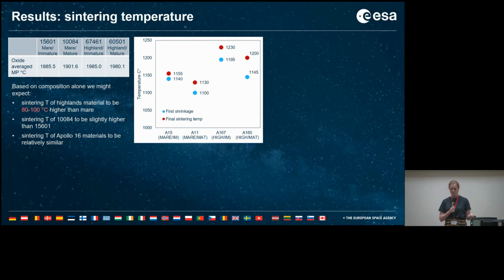So the red being the final sintering point when the material was very well sintered, and the blue being the sintering onset, so when it first shrunk away from the walls of the crucible and was removable as a pellet. And so here we can see that the Highlands material in general does sinter at a higher temperature than the Mare material. That can be reasonably well predicted with the composition. However, the other two predictions, we don't see that at all. So we would expect the Apollo 11 to have a higher sintering temperature than Apollo 15, but in fact it's quite a bit lower. And we see quite a variation in the Apollo 16 materials as well.